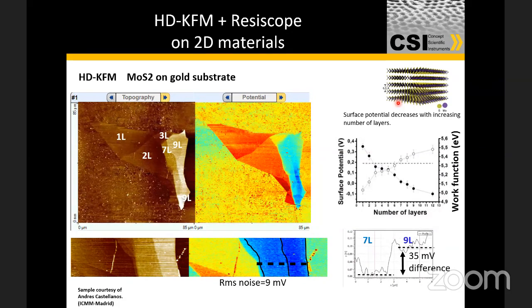So if you see this graph where you see 7 layer, 9 layer, that actually is Kunal trying to show how you can differentiate between 7 layer and 9 layer, the subtle differences in surface potential. So you can see surface potential as well as work function difference when the number of layers of MoS2 on gold keep on increasing. So I'm really impressed with this result actually. Mind-boggling. Yeah, very nice.